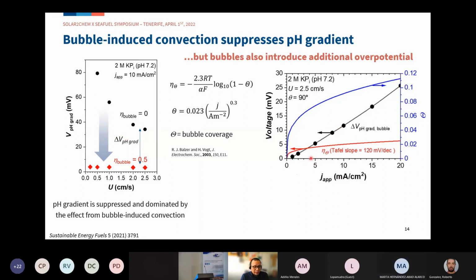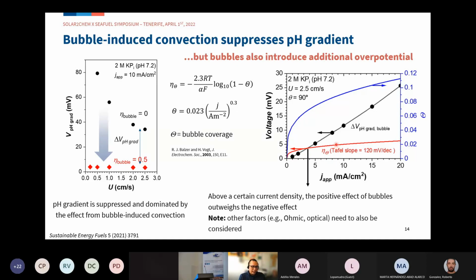So this simple analysis shows that above a certain current density, the positive effect of bubbles outweighs the negative effect. For different configurations, of course, this analysis needs to be done, and we need to optimize this in a way that the positive effect would overcome the negative effect. Also note that here we only consider the two factors of bubbles, but other factors such as ohmic losses and optical losses also need to be considered.